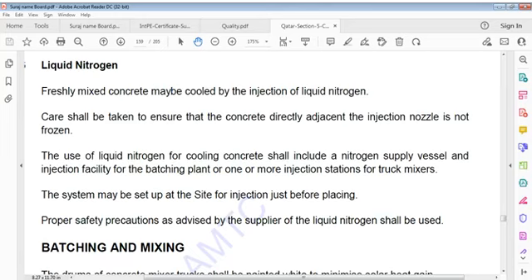Freshly mixed concrete may be cooled by injection of liquid nitrogen. Care shall be taken to ensure that concrete directly adjacent to injection nozzle is not frozen. Use of liquid nitrogen for cooling concrete shall include a nitrogen supply vessel and injection facility for batching plant or one or more injection stations for truck mixers. System may be set up at site for injection just before placing. Proper safety precautions as advised by supplier of liquid nitrogen shall be used.